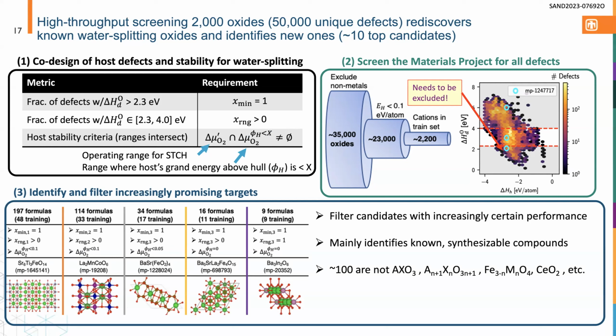So, we apply these increasingly strict down selection criteria. You can start with anywhere from maybe 200 materials down to only 10, depending on how strictly you apply these stability and defect range criteria. So we increasingly filter certain candidates that we think are potentially good water splitters.